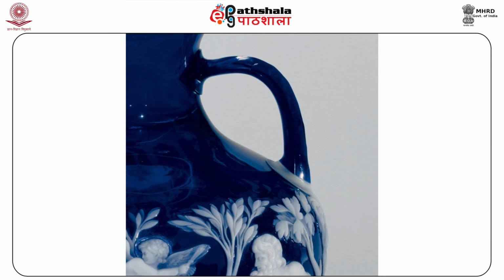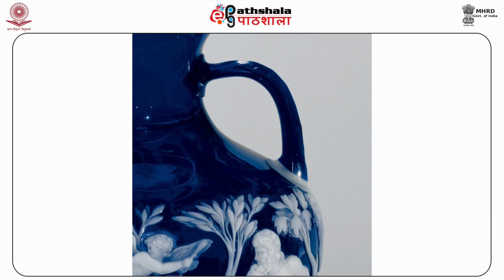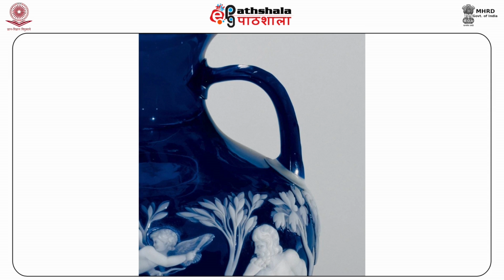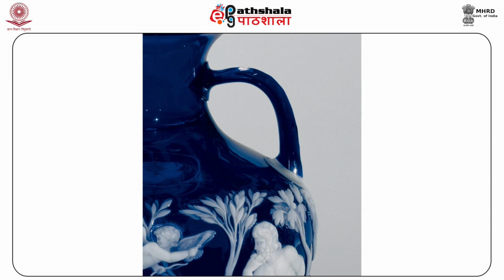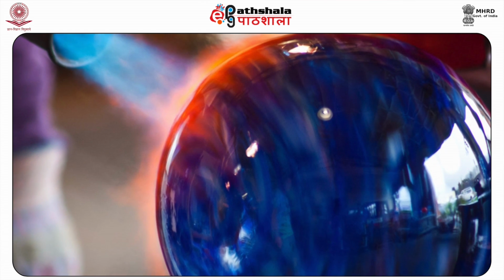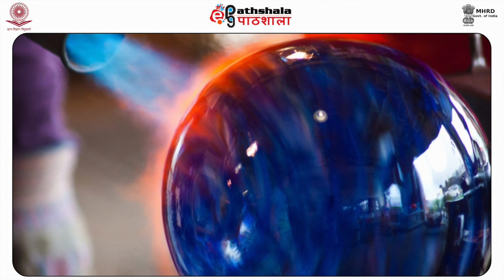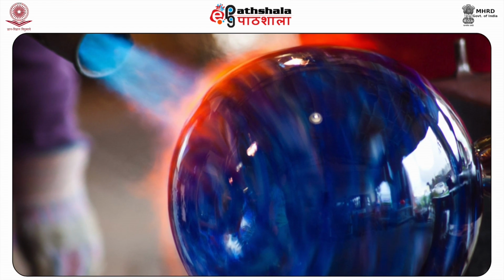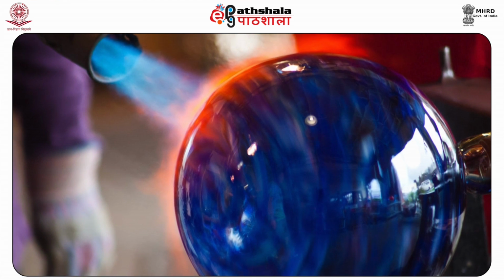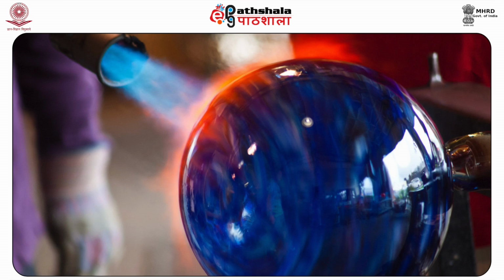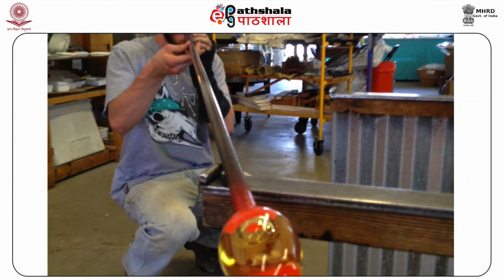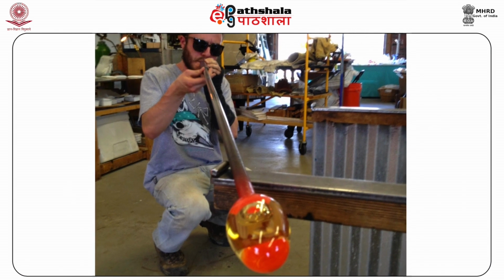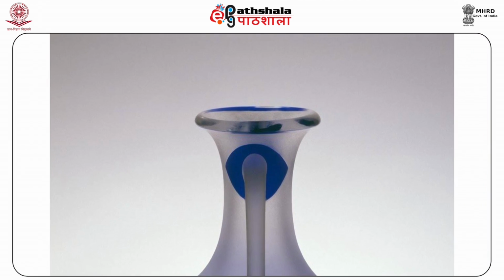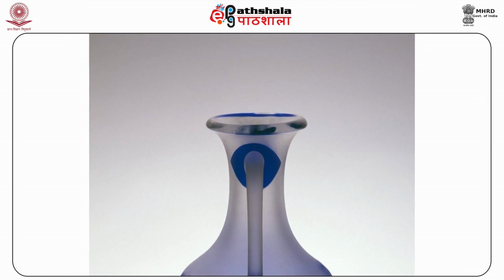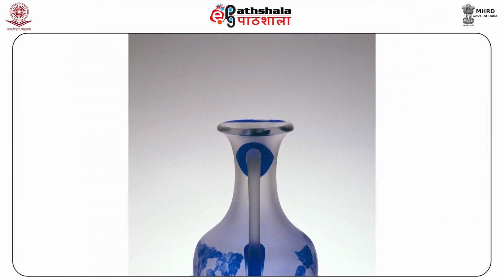Experimentation was carried out by Gudenrath and Whitehouse with the purpose of reinventing the Portland vase. Mainly, the blue glass needed for the body of the vase was collected on the end of the blowpipe that was consequently immersed in a container having hot white glass. Inflation took place when the glass worker blew the melted glass into a sphere. The sphere was then stretched or elongated into a vase with a layer of white glass overlying the blue body.